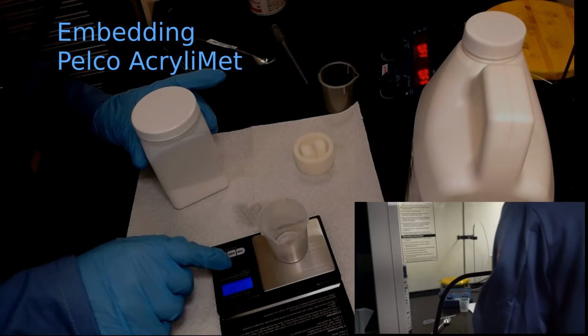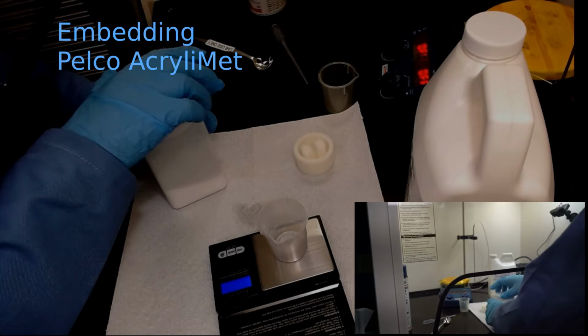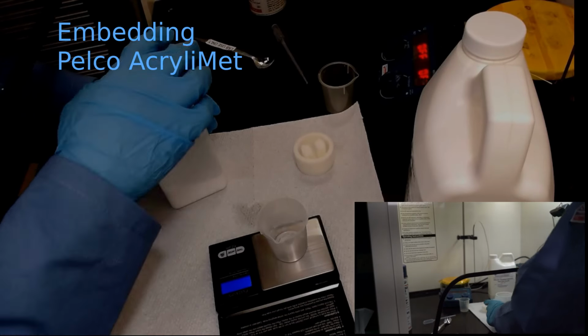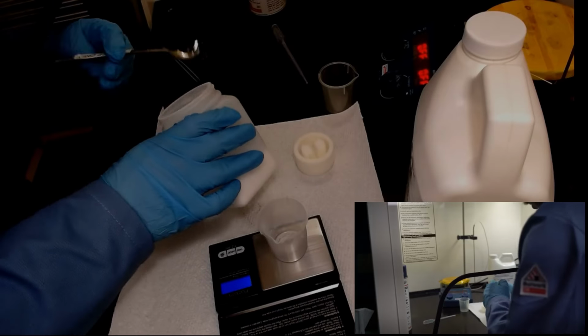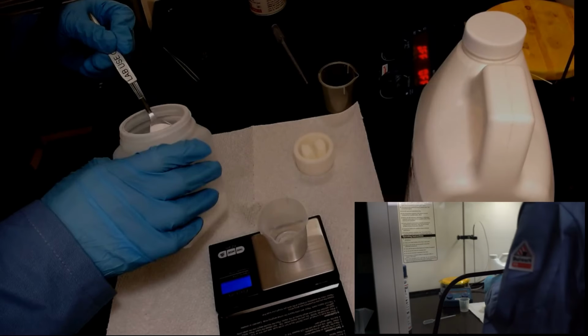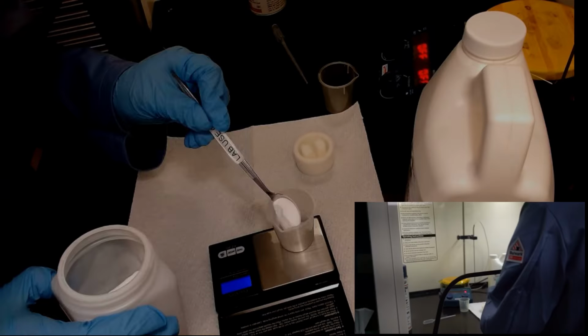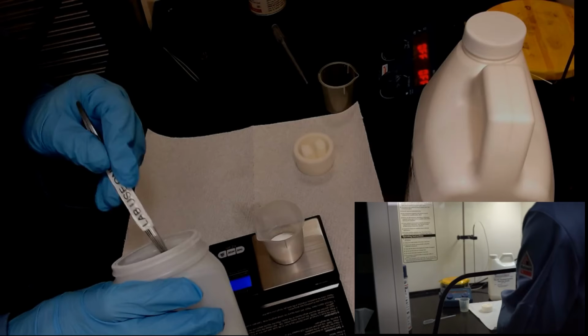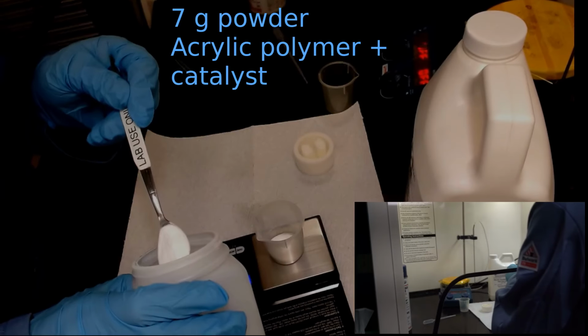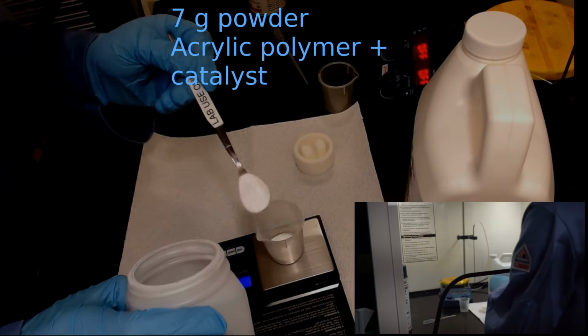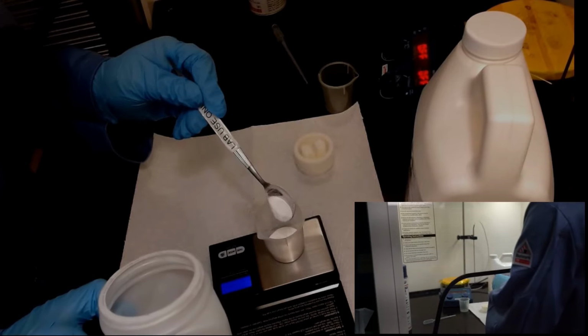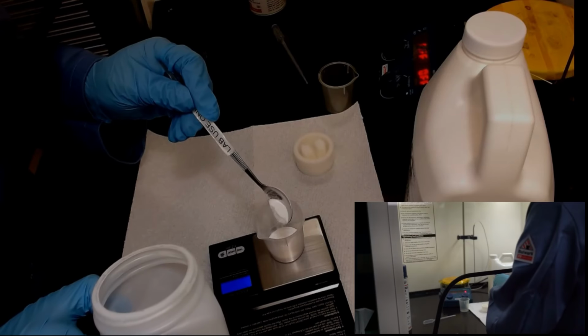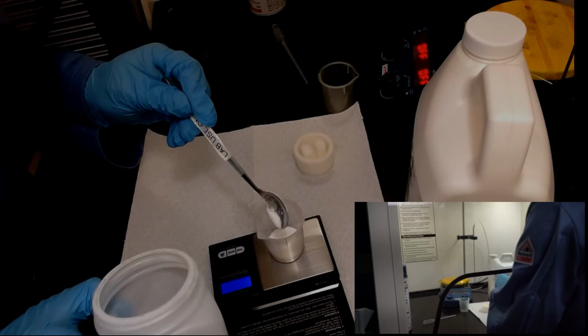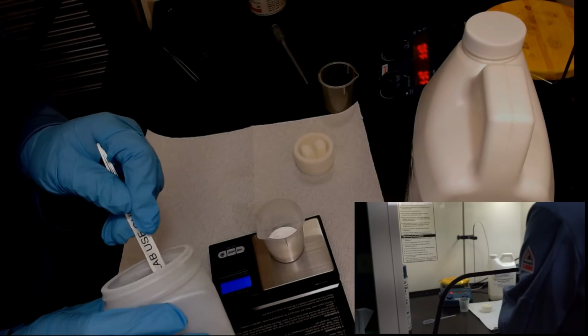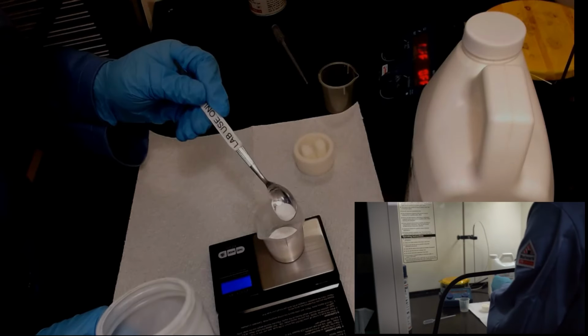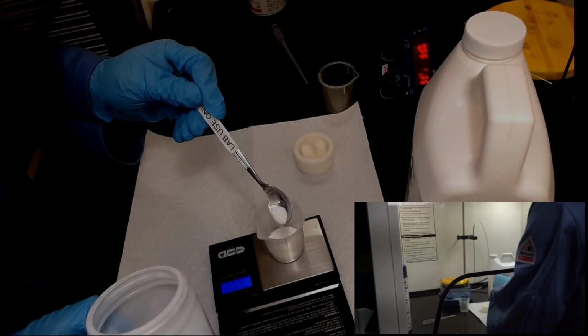All of the measurements are done by weight, makes things nice and easy. We don't have to worry about trying to measure precise volumes, especially because the powder is pretty fluffy and very bulky. You do want to be careful doing this in a fume hood. The particulates do try to blow around a little bit in the airflow, so try and make sure that you aren't pouring a long distance from your scoop into the beaker. Otherwise, it blows all over the place and makes a big mess of your hood. Ask me how I know.